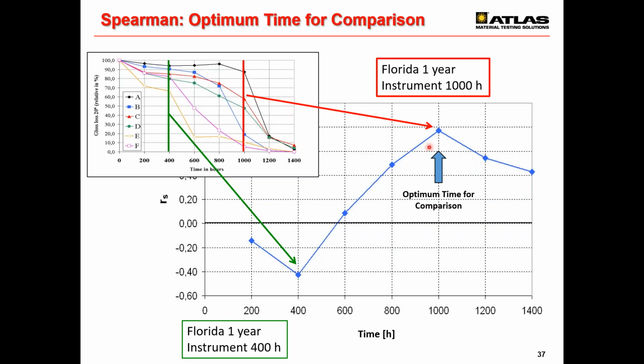Then it's dropping again. So that would be the best time to compare Florida outdoor weathering to the artificial weathering, to the xenon arc exposure. 1,000 hours in the instrument and 1 year Florida show the best comparable ranking of the materials.